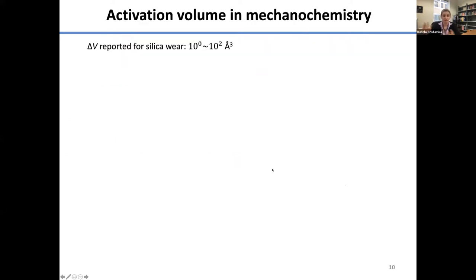Because if you look at experiments of wear of silica and the values that people extract from it to understand how the stresses affect the reactivity of silica, you see that the activation volume can vary by two orders of magnitude, right? So something is going on. And so we wanted to understand it because, again, this is going to change the design principles for understanding and controlling tribochemical reactions. So we wanted to understand it.